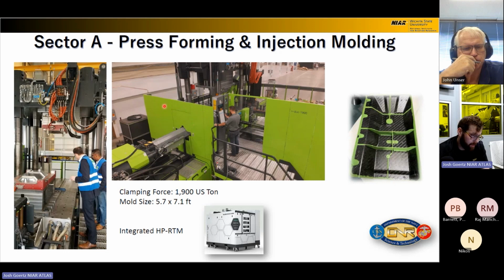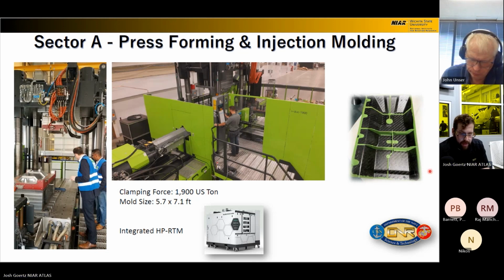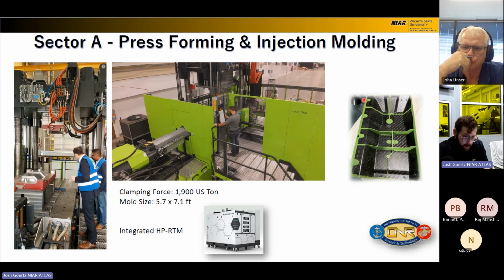And then, in addition to that, on the backside of the machine, there's also a high pressure resin transfer molding pump, where we can take a dry fiber blank in an encapsulated mold and inject it with a thermoset resin. This example part on the right here is a thermoplastic cloth blank that's been stamp formed in this shape, and then it gets transferred to a second mold where this green material is injection molded on top of it. That's a chop fiber material for your stiffening ribs and mounting features.